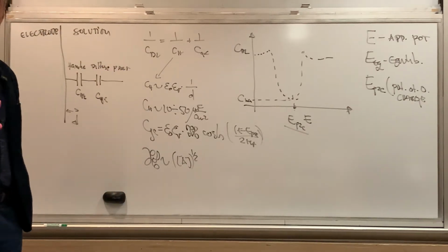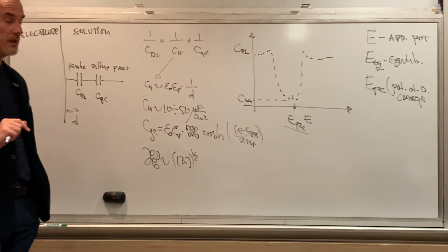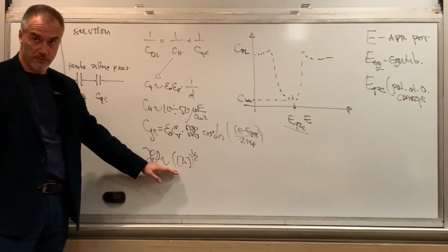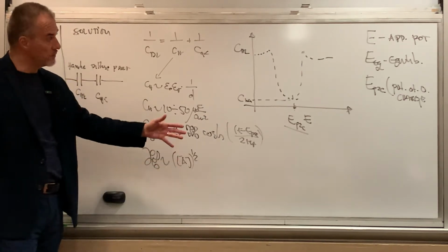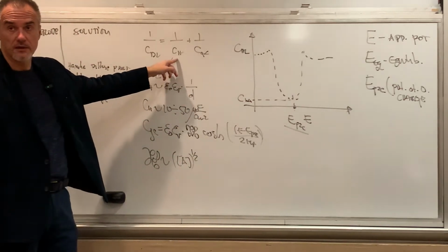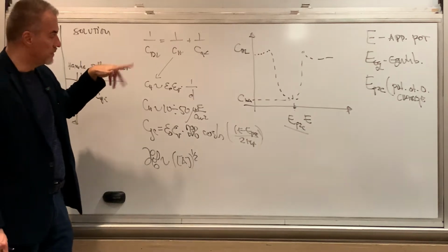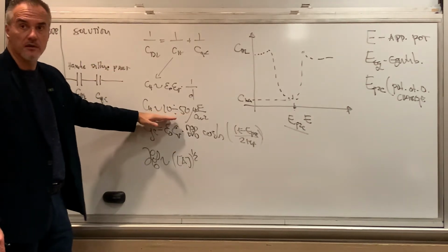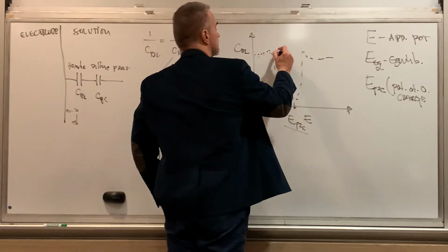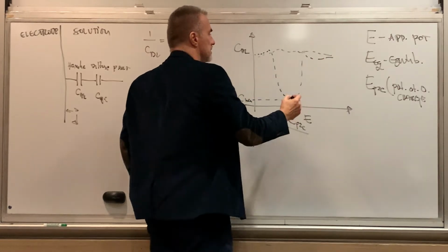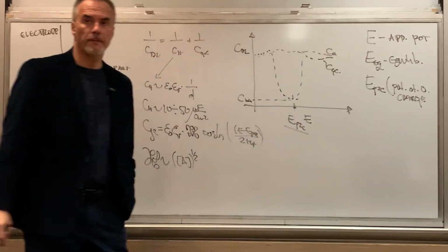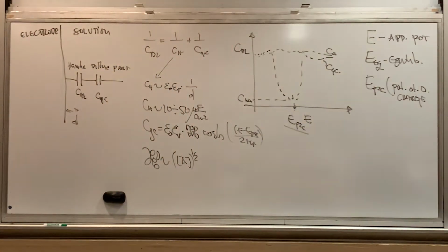So obviously the double layer capacity, which we can measure experimentally for low concentrations, has some kind of a minimum. As I told you before, if the concentration is very high, the Helmholtz layer is the dominant contribution that we measure, and that is basically potential independent, right? It looks constant. So maybe it looks something like this, relatively potential independent, when this is a C H and this is a C GC. So it depends what kind of concentration of the electrolyte we have in solution.